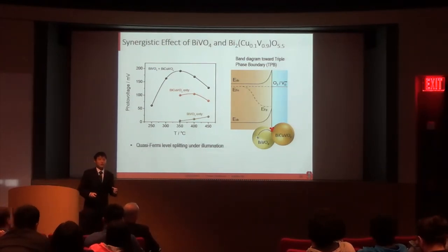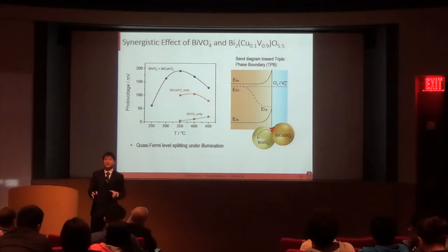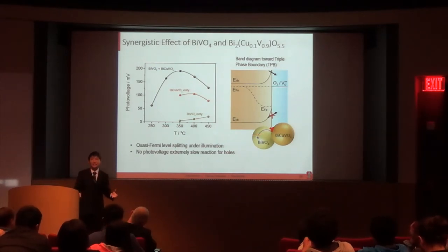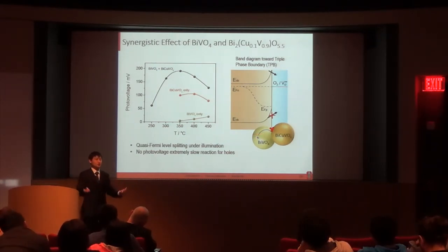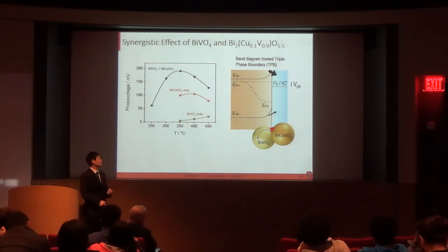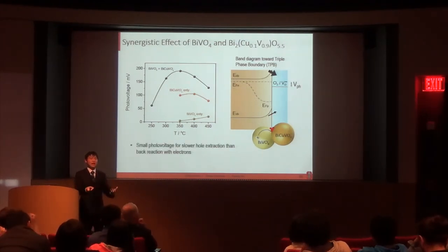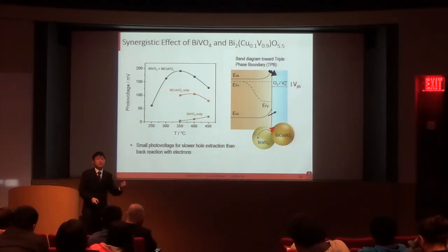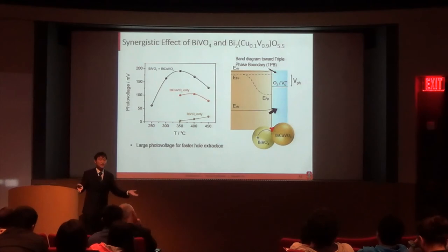Under illumination, the quasi-Fermi level splitting will be created within the semiconductor, but it does not necessarily translate to a photovoltage. Imagine, if the reaction kinetics is extremely slow, so no hole can be extracted, then there will be no photovoltage to be measured. If there's some hole extraction rate or some reaction happens at this interface, we can observe some photovoltage. But this photovoltage can be very small if the back reaction with electrons dominates. Ideally, we want a faster hole extraction rate compared to the back reaction with electrons, so that we can observe a larger photovoltage.